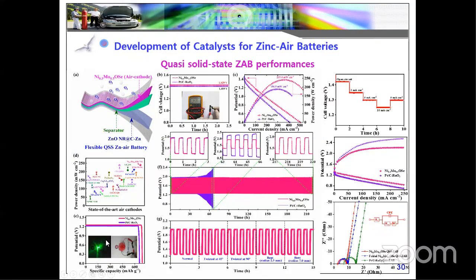And we also performed the practical applicability test, lighting an LED, and the toy fan ran effectively, and the LED also glowed for almost 24 hours. For the charge-discharge, from the long-term discharging curve we calculate the specific capacity, and from the specific capacity we calculate the energy density.